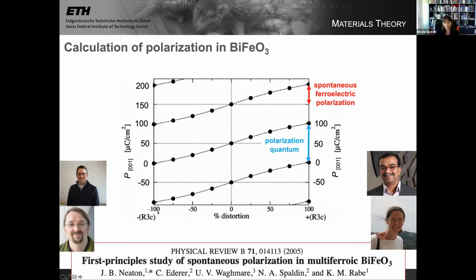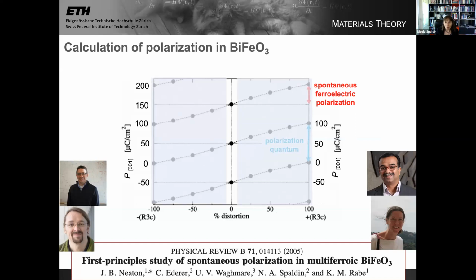And the x-axis here is the percentage of distortion, where 0 represents the centrosymmetric paraelectric structure, so with no polarization, and then plus R3C is just the space group of the ground state, plus 100 means the system is completely relaxed to its ground state with the polarization in one direction, and minus 100 is with the polarization reversed in the opposite direction. So the ferroelectric polarization switch. Okay, so I want to point out a couple of things.